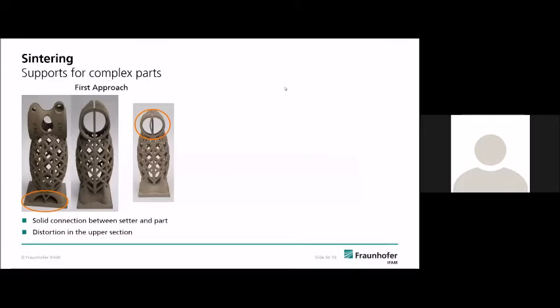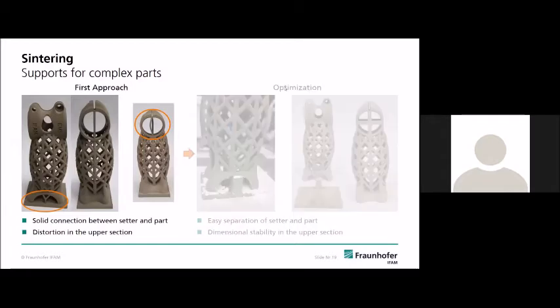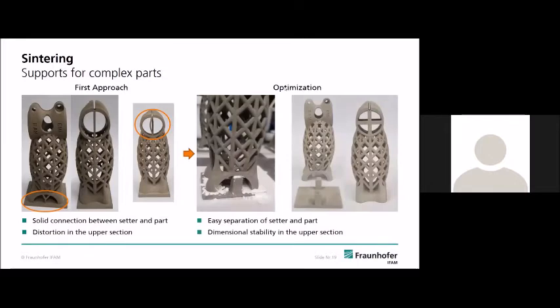I was talking about support structures we don't need. This is not the whole truth, because during sintering, gravity exists as on the whole planet, and the structures get weak during sintering due to the high temperatures, and sometimes you can lose your geometrical accuracy while sintering. So sometimes you have to use even here support structures, or you have to work with so-called setters under your green part during sintering to keep the quality of your geometry. But you need much less support structures than for the beam-based processes.